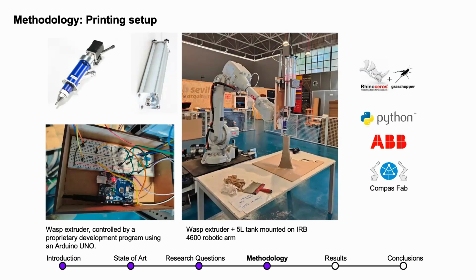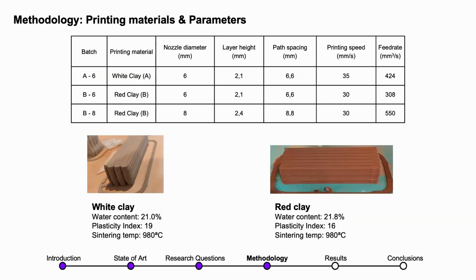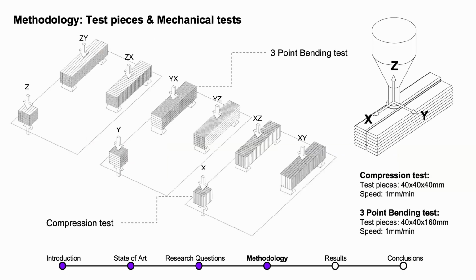The printing setup is like this. We have a 5-liter pneumatic tank controlled by an Arduino and mounted to an ABB robotic arm. And with all this software, we created a new workflow, very friendly to designers and for digital fabrication purposes. We manufactured three different batches, by the combination of 2 printing materials and 2 different printing nozzle diameters. We used white clay and red clay, both reaching a maximum sintering temperature of 980, and with these printing parameters.